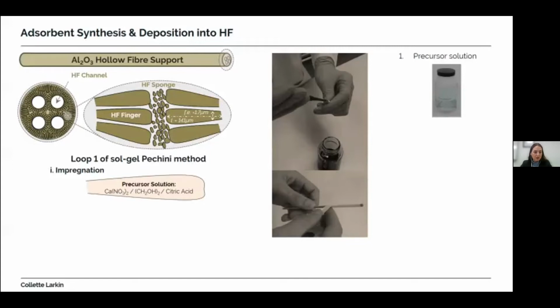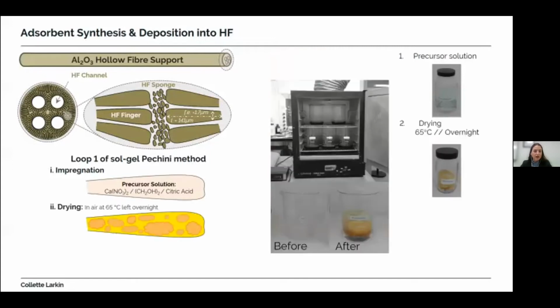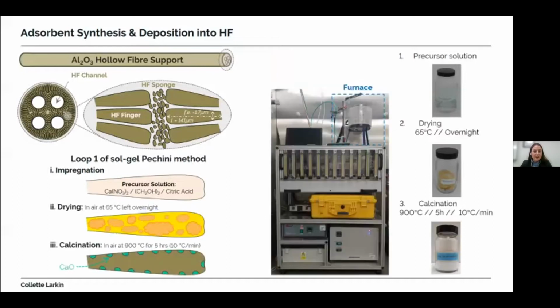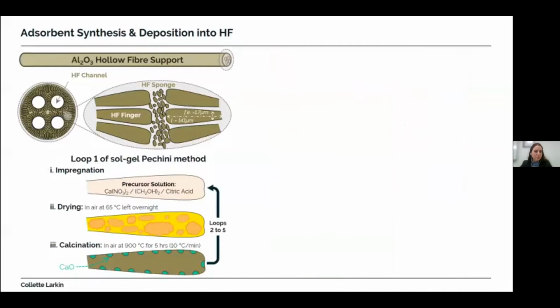The second step was to let the precursor solution dry in an air atmosphere overnight at 65 degrees. This produced an orange cake. And thirdly, the cake was calcined in an air atmosphere at 900 degrees Celsius for 5 hours. This produced the characteristically white calcium oxide solid and formed the hollow fibre adsorption unit. The same method was used to create the pellets for the packed bed adsorption unit, except that was all undertaken inside a beaker. But how do we know if one impregnation loop is the most optimum?